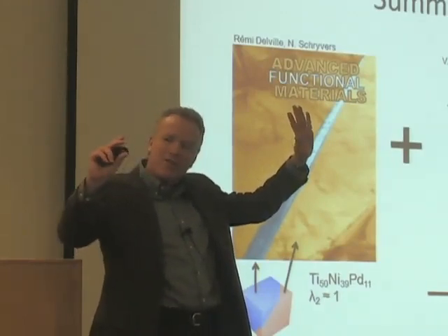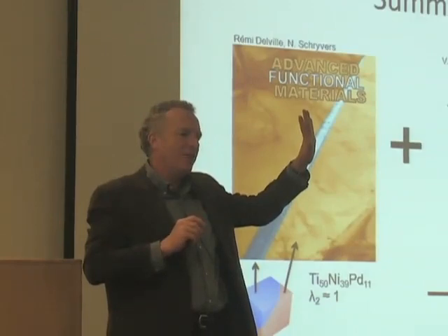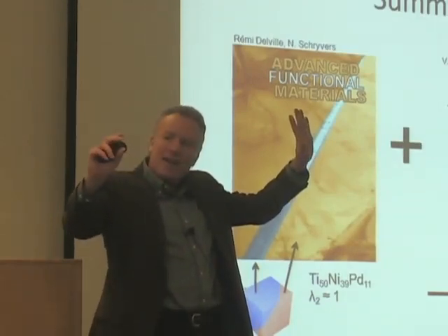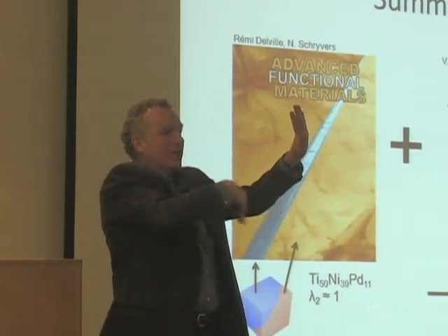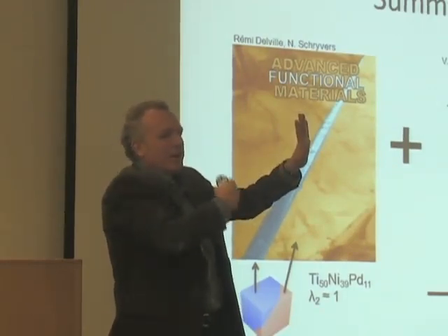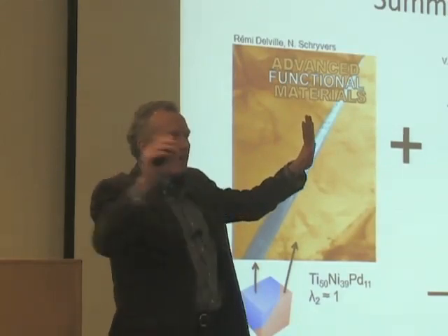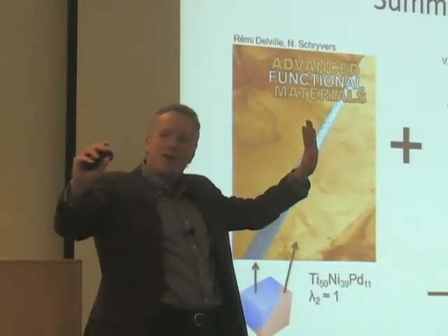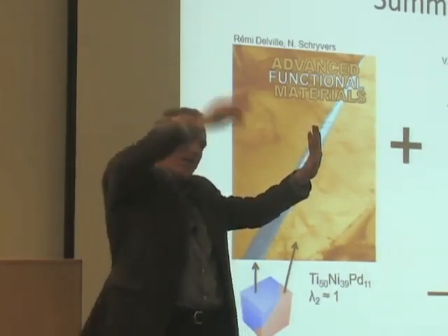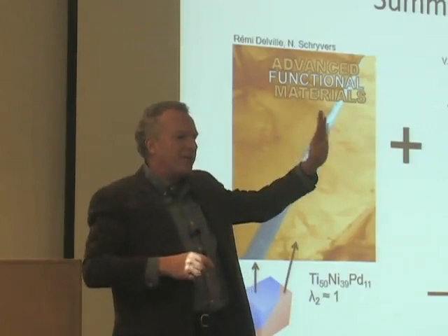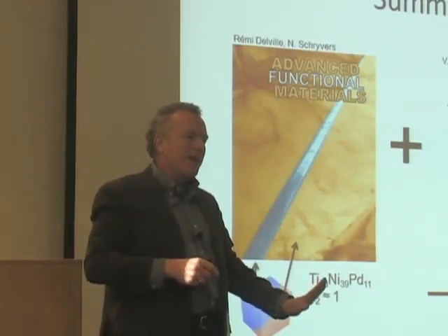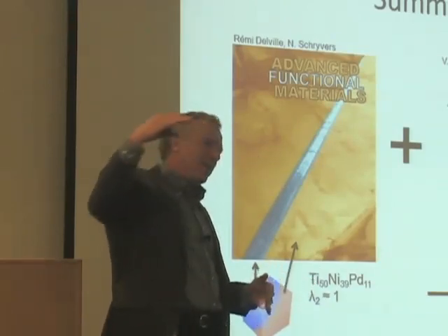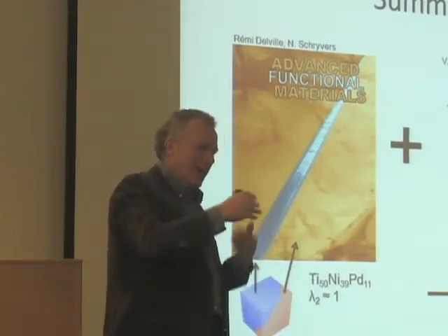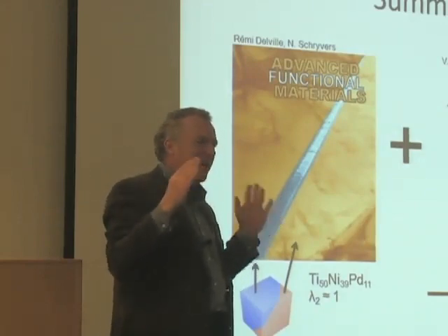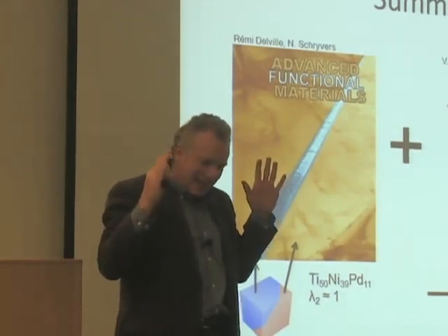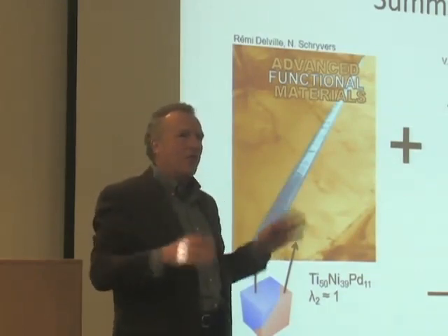And the reason is that the more bands near the interface, the better, because you can reduce the elastic energy. So if you can imagine a branching phenomenon where a few bands over here got finer and finer and finer as you approach the interface, you would have the benefits of very small elastic energy. And you wouldn't pay too much interfacial energy because the number of interfaces would be graded. If this is done in exactly the right way, you can show, at least under some hypotheses on elastic moduli and so forth, that it is energetically favorable to do this kind of branching. And that's believed to be the explanation in the other case.